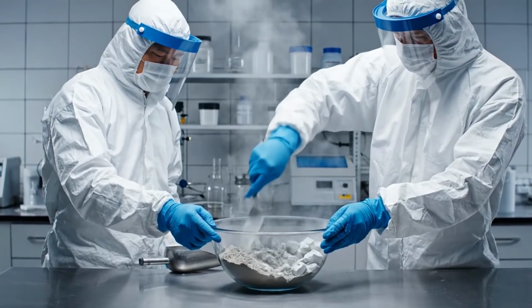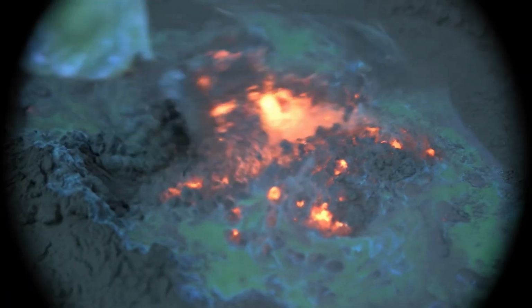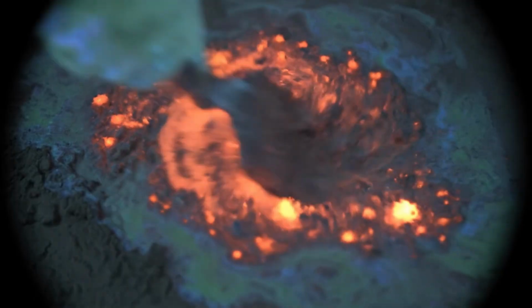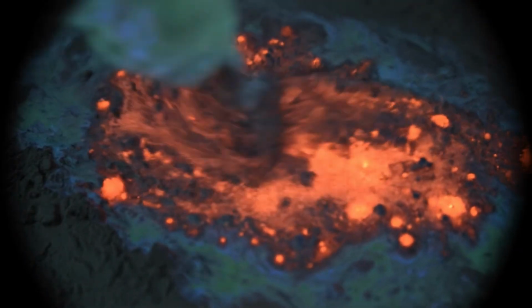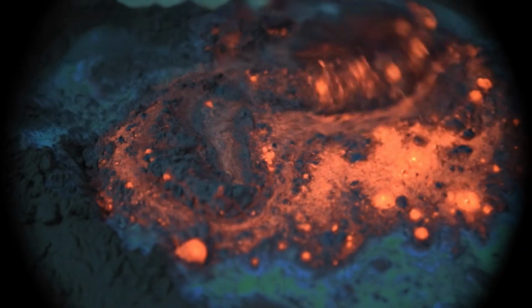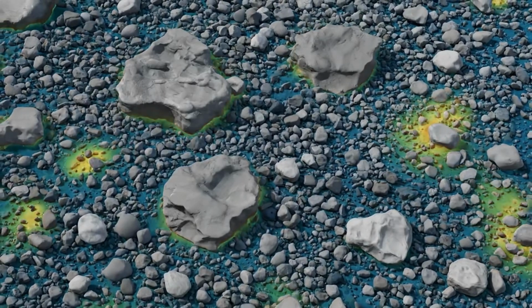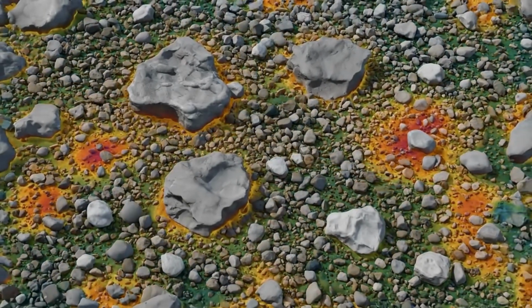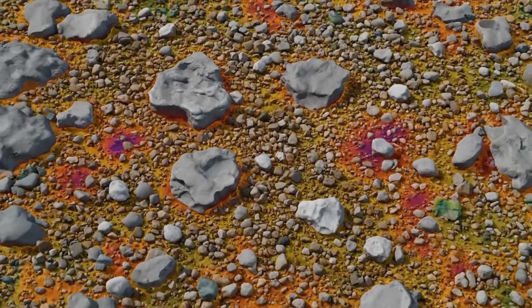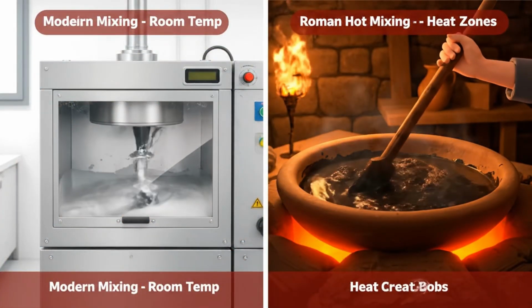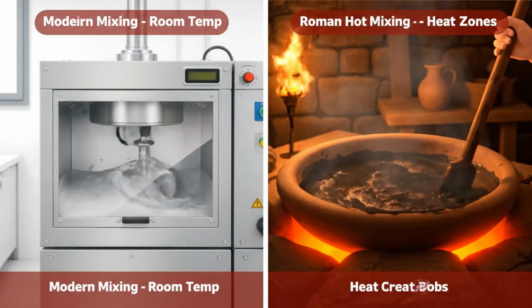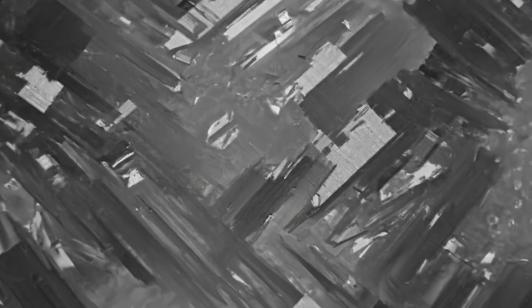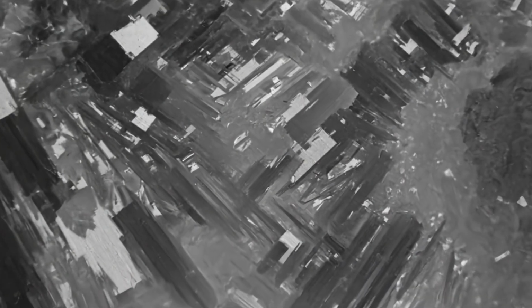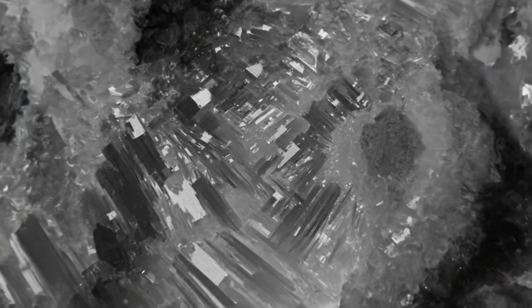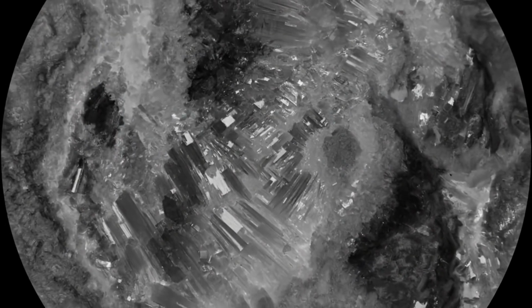They deliberately added reactive quicklime chunks directly into wet concrete. The heat from the lime-water reaction created localized high-temperature zones throughout the mixture. This wasn't incompetence, it was revolutionary materials engineering. Because here's what happens when you hot mix. First, the extreme heat accelerates the pozzolanic reaction in those zones, creating ultra-dense binding regions stronger than anything in modern concrete. Second, and this is the key, some quicklime never fully reacts.